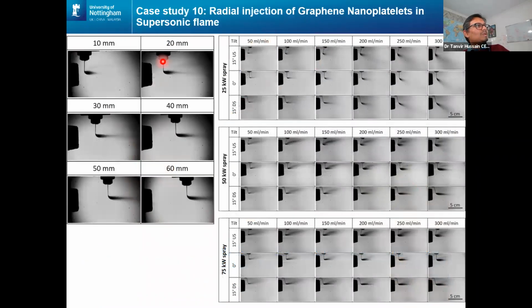We then went further and tried to develop a system where we're injecting graphene nanoplatelet suspension directly in the flame. Because it's a carbon-based material, it doesn't like high temperature, so when we inject it axially, it doesn't work very well. So we were playing with the distance, moving from 10 millimeter all the way to 60 millimeter, and seeing how the suspension breaks up when we inject it. We are working with different flame powers, 25 kilowatt, 50 kilowatt, and 75 kilowatt, and also different suspension flow rates, to understand what condition is required to develop a GNP film on a surface.